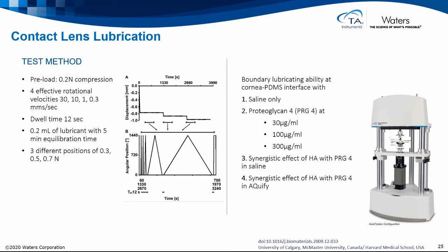So on the test method side, we see this combination of that linear motor on the top is programmed to do different forces. So that's like normal force in a friction equation. And then you're spinning that rotational motor below at different rates, and you can convert those to millimeters per second. You can see this sequence of events, and the software allows you to sequence this both with sliding velocity as a variable and axial or normal force as a variable. So you can do this all in one test experiment. And you can see the plots later will allow us then to pick apart these different variables. So that's how the test method is executed on this instrument.